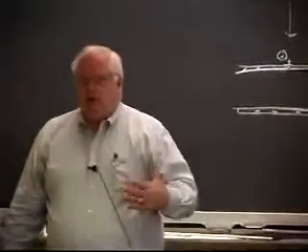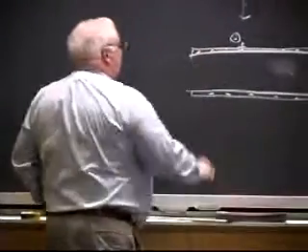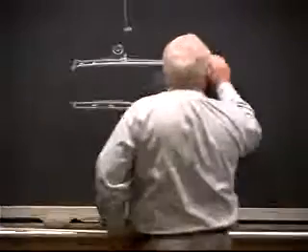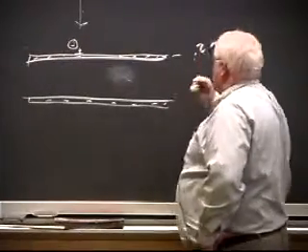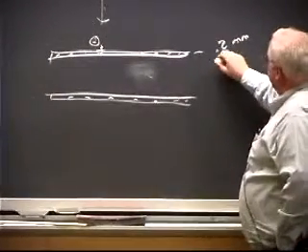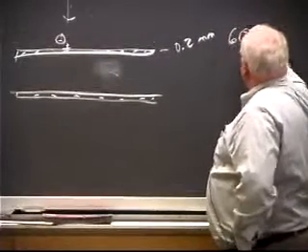Well, the problem was they'd never had any real problem for a long time doing this, and all of a sudden, every piece of paper that came out would have a few little black specks. Now, you and I probably wouldn't even notice them, but if you're doing quality control, the same spot every time off that drum would have a toner particle. And so they asked me to come up and look at this, and it turns out this coating was only about 0.2 millimeters thick. It's like 8 thousandths thick. So a couple of sheets of paper. And they had 600 volts across this thing in order to develop the charge.